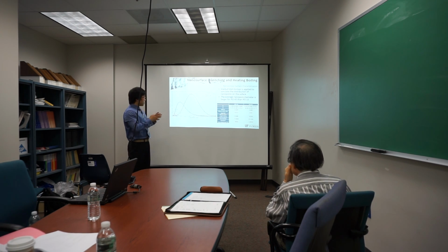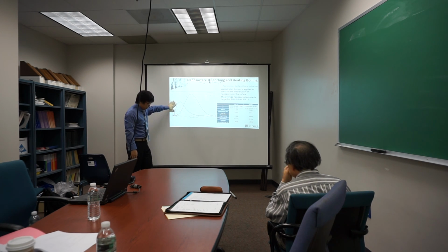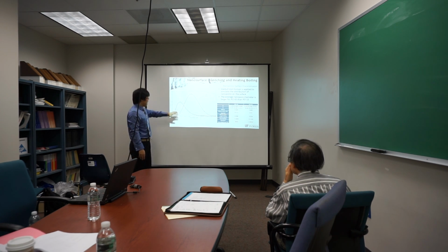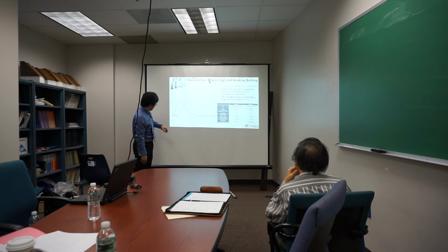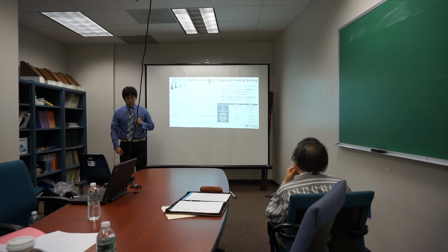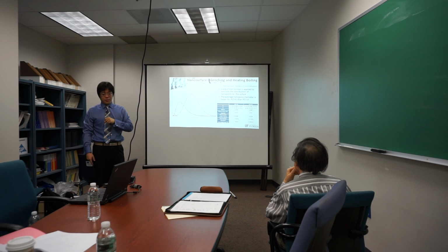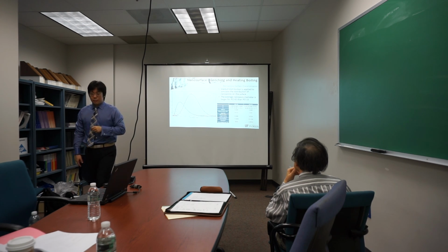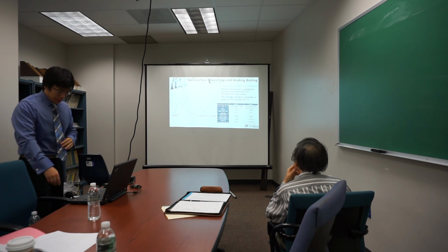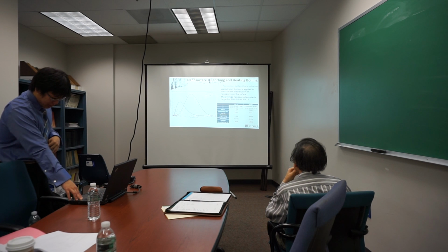And we can see that for PO15, most of the sizes are very tiny compared to PO45. It's around 0.01 microns, but PO45 is around 0.025 or 0.030 microns. So this parameter will be very important, and we will see that one again.